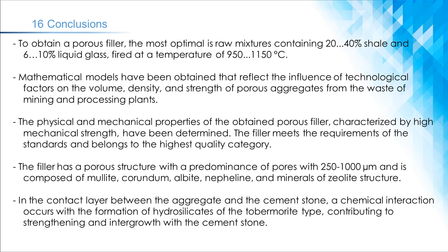The filler has a porous structure with a predominance of pores with 250–1000 microns and is composed of mullite, corundum, albite, nepheline, and minerals of zeolite structure. In the contact layer between the aggregate and the cement stone, a chemical interaction occurs with the formation of hydrosilicates of the tobermorite type, contributing to strengthening and intergrowth with the cement stone.